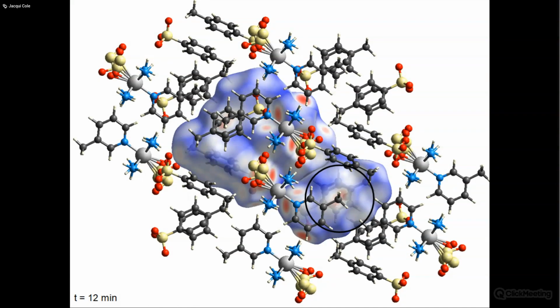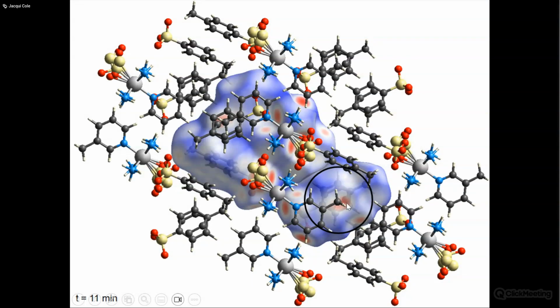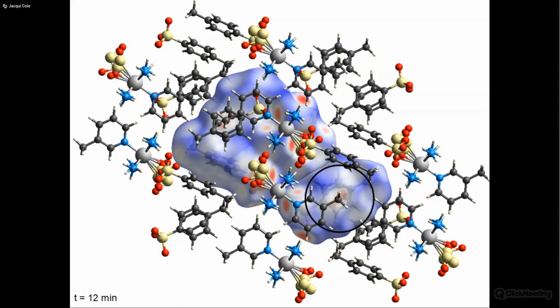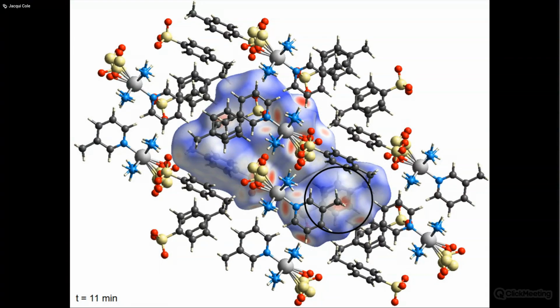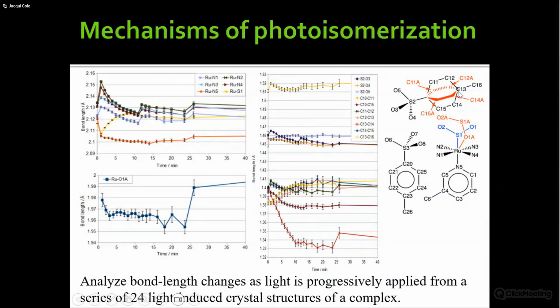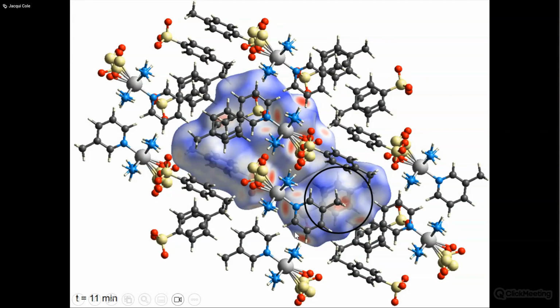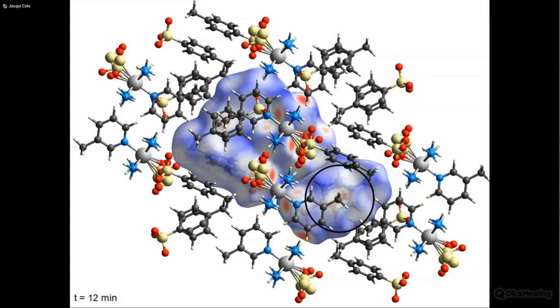I'm going to go backwards, back to 11. You see that methyl group, the methyl group from the substitution onto the pyridine ring. That's pretty much right on top of the arene ring. Can you see that they've got that steric disorder underneath it? This is 11 minutes, and you see 12 minutes. The red just changes, and there's a little rotation of the methyl group, it seems, as well. But I think really it's the bonding of the arene ring which you do see. If I go back quickly, you'll see this drop here. That's all I can see. I've literally looked at every single bond length and that interaction. So there's some very subtle interaction there that is seemingly the only thing changing, but it's consistent with those bond lengths.